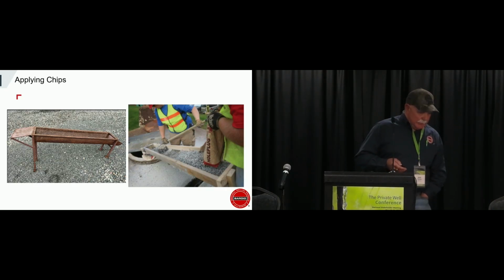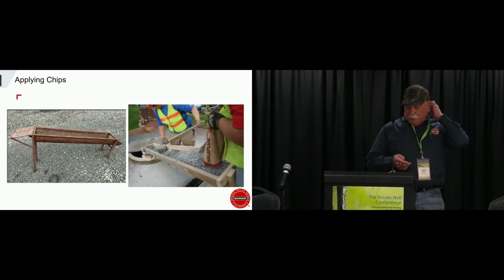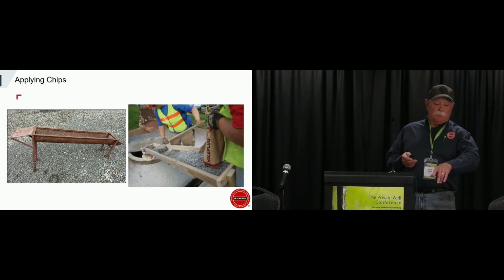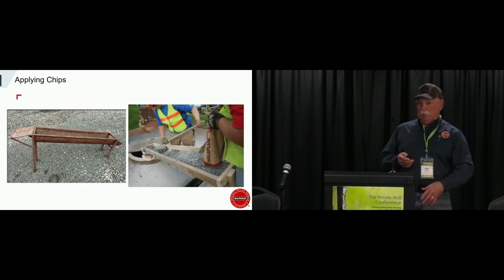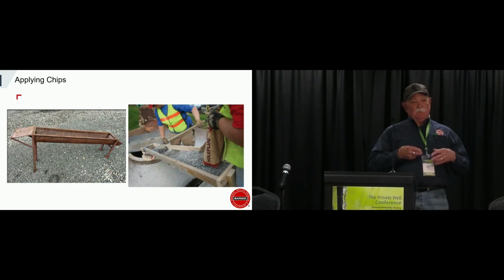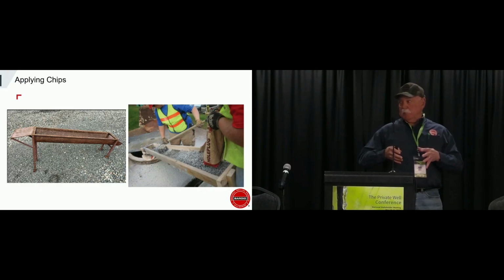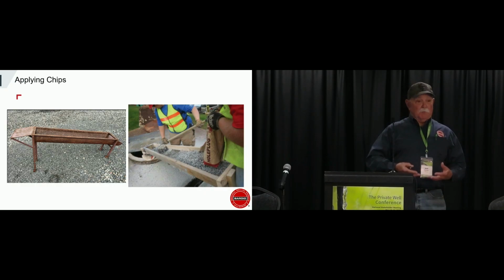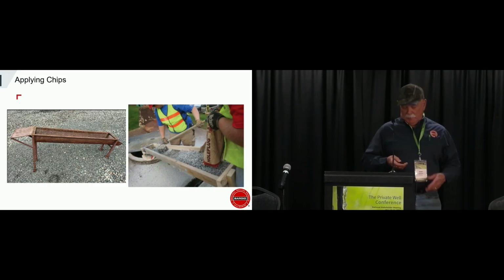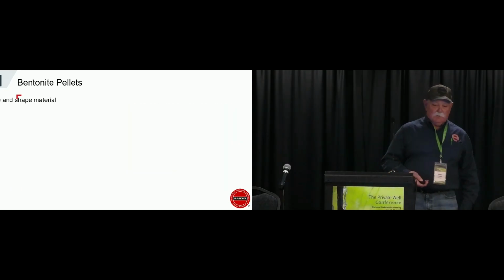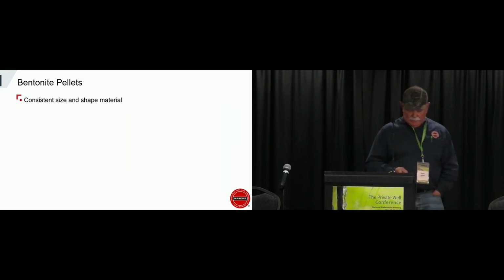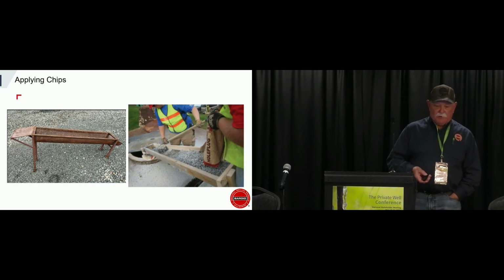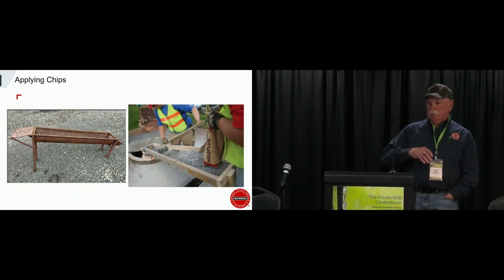So here's a couple of pictures of a device where you could put the chip bentonite across that expanded metal screen, and if there's any dust in the sack, it's removed before it starts traveling down. Like I said, bentonite is a viscosifier, so if you viscosify the water in your annular space, it will slow the migration of the bentonite down to the bottom of the hole, which could cause bridging, which could cause not a very good seal. I've seen quite a few of these different types of devices, anything made out of sewer pipe or whatever, but just to get the dust out, and then figure out 2 to 3 minutes per sack to put that down the hole.